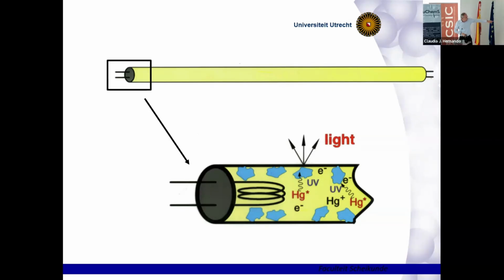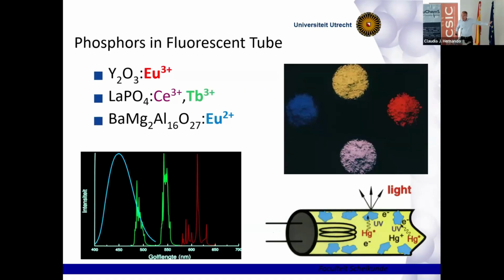So on the inside of the fluorescent tube, there's a coating of phosphors, of luminescent materials that absorb the UV and convert UV radiation into red, green, and blue light. And then, if you combine it in the right ratio, you get white light. The phosphors that are used in all compact fluorescent tubes and fluorescent tubes are yttrium oxide with europium for the red light, lanthanum phosphate with cerium and terbium. Cerium absorbs UV, transfers the energy to terbium, terbium emits green light, and barium magnesium aluminate with europium 2+, absorbing UV and emitting blue light. And if you mix them in the right ratio, 2 scoops of red, 2 scoops of green, 1 scoop of blue, mix it up, then you get a white luminescent material.